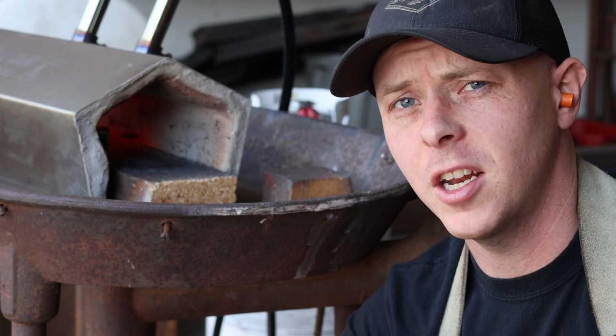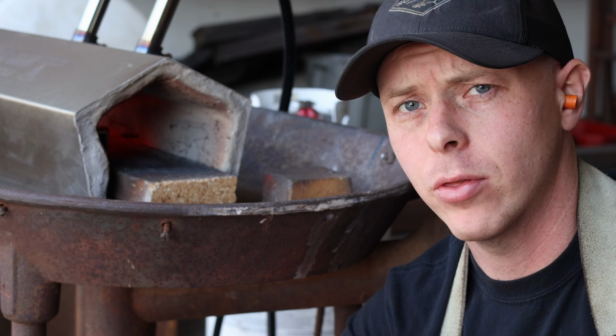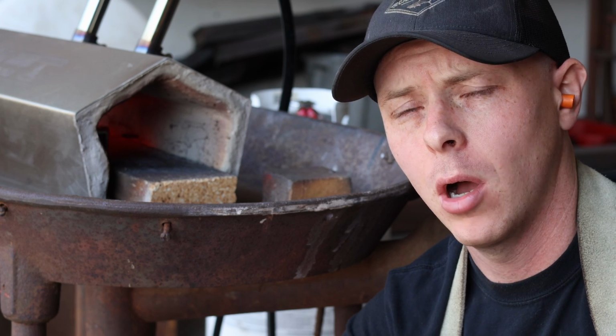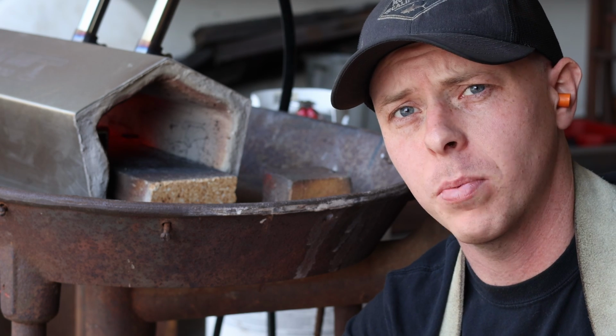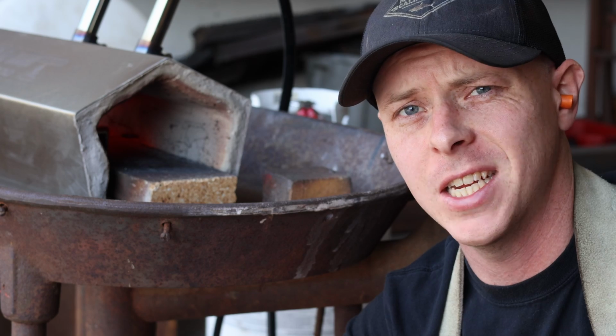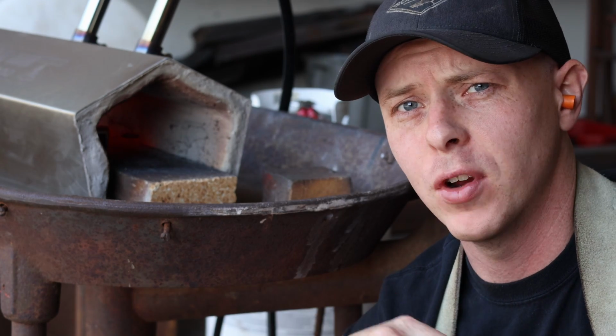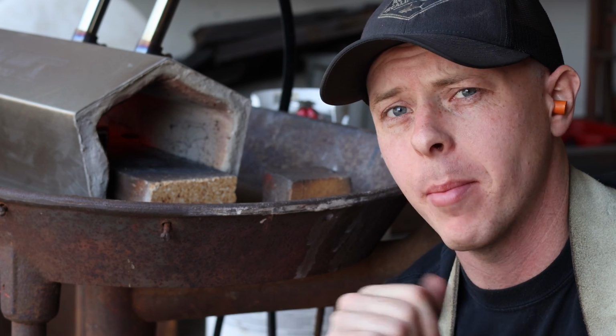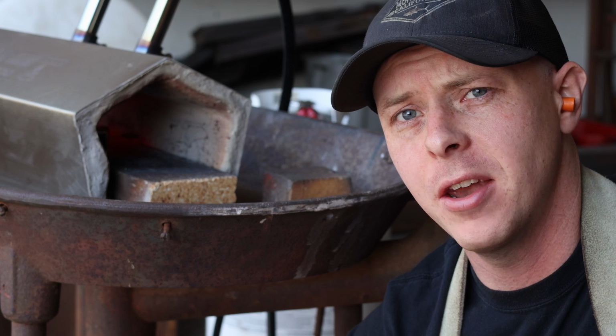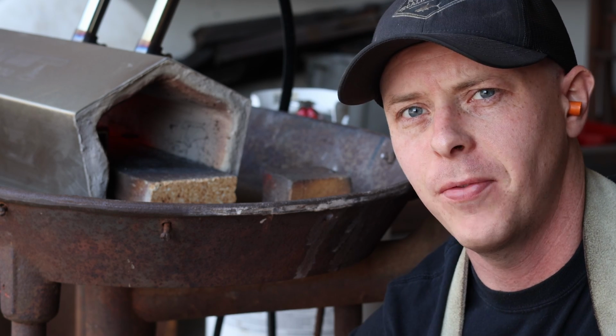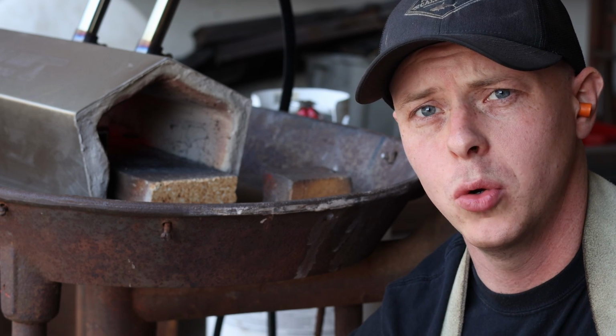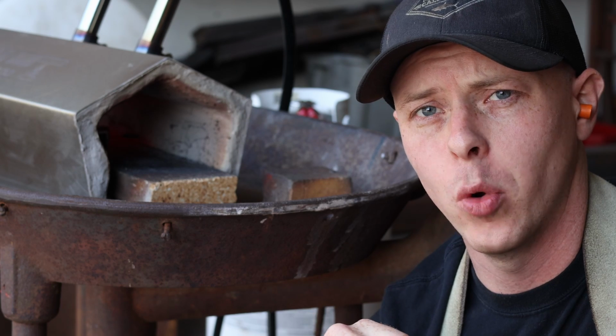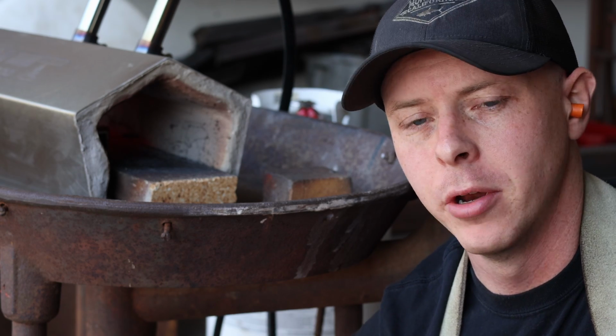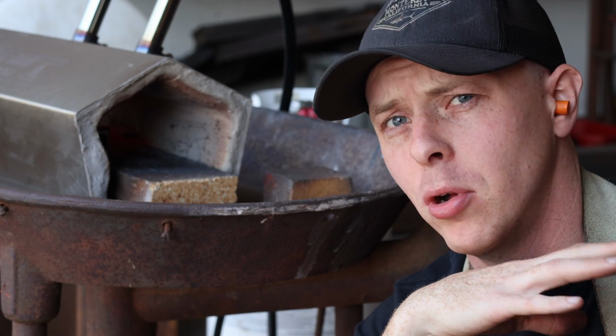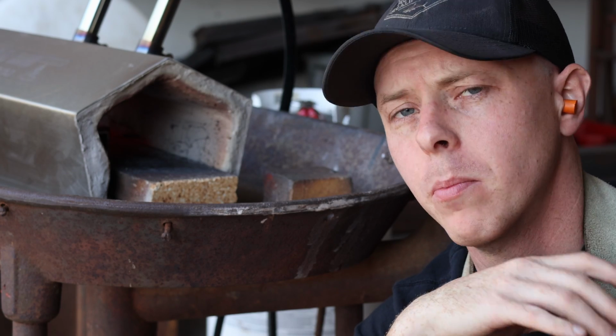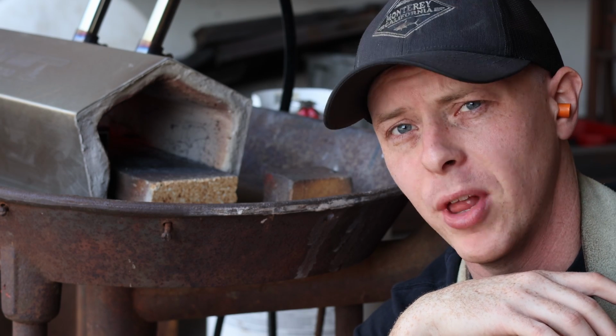Well, about 2 minutes into my soak period, my thermocouple failed hard. It was bouncing back and forth between 1,000 degrees, 1500, 1700, all over the place every second. So I'm going back to winging it and doing everything by eye. So I just finished my 10-minute soak window at about 1650, and I'm letting it cool down to a black heat, and I'm gonna do another one at about 1500. But yeah, the thermocouple breaking kind of threw a wrench in all of my plans today.